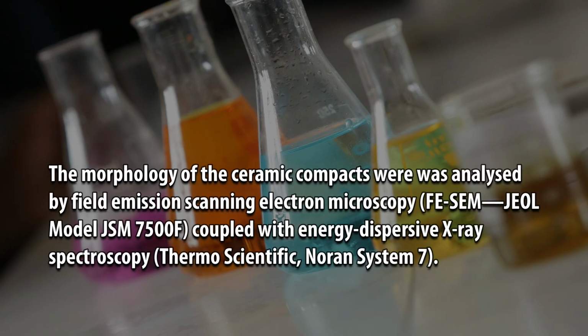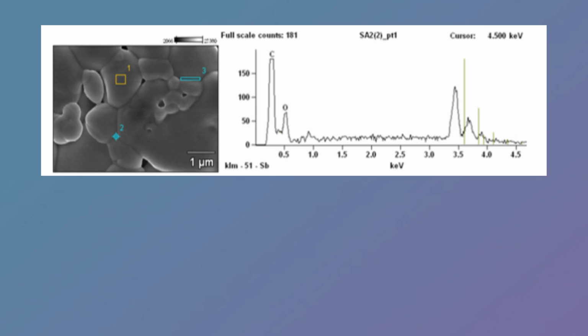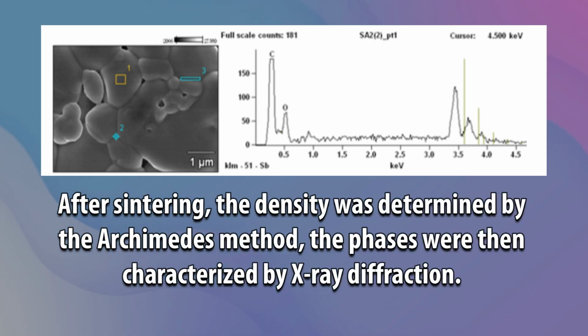The morphology of the ceramic compacts was analyzed by field emission scanning electron microscopy, FESEM, JEOL model JSM7500F, coupled with energy dispersive X-ray spectroscopy, Thermo Scientific, Noran System 7. After sintering, the density was determined by the Archimedes method. The phases were then characterized by X-ray diffraction.